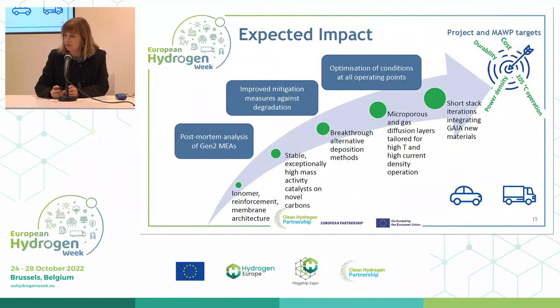So in terms of the impact there, the main steps, or some of the steps, let's say, are written up there on that final slide. As I said, the post-mortem analysis was important. That allows us to integrate improved mitigation measures. There was also optimization of operation conditions. Certainly in terms of the materials development, there was the work on the ionomer, the reinforcement, and the membrane and the membrane architecture itself, the development on the catalysts, breakthrough alternative deposition methods, breakthrough in terms of MPL and GDL that were tailored for these particular conditions of high current density operation and the high temperature. And then finally all the work on integrating all of this, making the MEAs and doing the testing. That allowed us to achieve, with stable operation, this 105 degrees operation, the power density, and definitely make improvements in terms of durability and move towards the cost target as well.